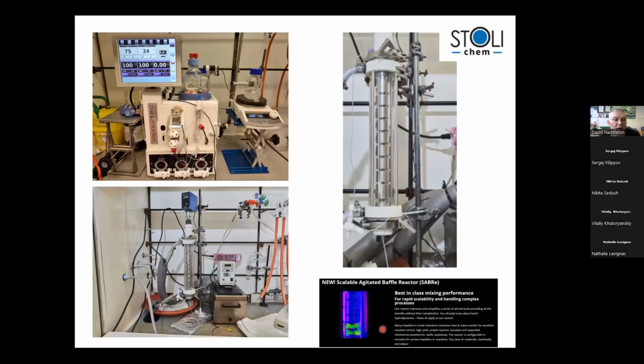So what do we do? My first foray, I won't spend too long on this, but we'll be doing this in flow, and flow is considered to be a more sustainable way of producing things than batch. We'll be flowing the reagents into that. This is a thermal reactor, and then we will do the chemistry in that. This is a plug flow reactor. Also doing this thing, which I quite like, where we flow the reagents up into the middle, we thermally equilibrate that at the temperature we require, and each one of these holes is a little batch reactor, and the batch reactor's then got its own stirrer.